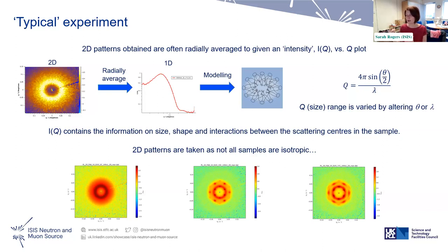That scattering pattern is then normally modeled. We have analysis software that the instrument scientist can help you use that can then give you a picture or an idea of what's going on in your sample. And as I said before, we have this parameter that I keep going on about called Q. Q is equal to 4 pi sine theta over 2 over lambda, where theta is the scattering angle and lambda is the wavelength of the neutrons. So basically, it's the size that you're interested in, and it's in reciprocal space. So the smaller the Q, the bigger the object that we're looking at. So never try and reverse your car in Q. You will undoubtedly crash it.